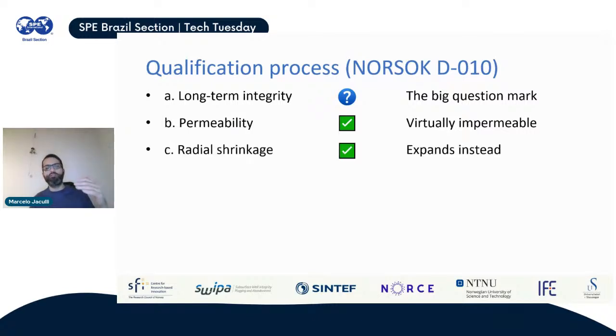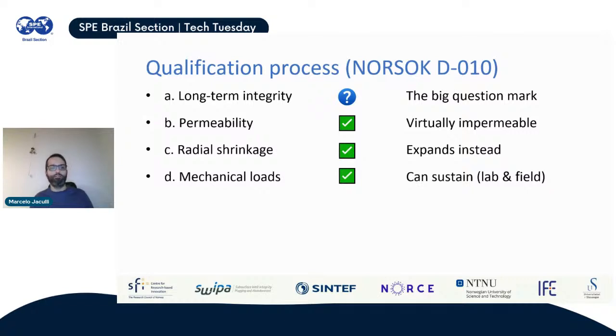An alternative material cannot have too much radial shrinkage. There is some accepted limit on this. You have shrinkage from cement, which is a well-known effect, and there are a lot of studies on how to improve the cement. There are a lot of additives that you can put in cement to combat this shrinkage. But for bismuth alloys, that's also solved from the very beginning because the alloy expands instead. So you have no problems with radial shrinkage. Then sustaining mechanical loads, that's up to the conditions where you're going to apply it. But in general, based on the lab tests that we did and on the field application from AkerBP, we can say that yes, the plug is able to sustain the mechanical loads that are expected from it, in the same way that cement can also withstand these mechanical loads. So for this one, we have collected a good amount of data to at least give some check mark. Sustaining the mechanical load is not the issue.